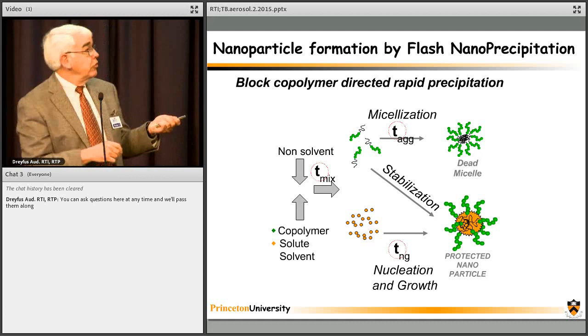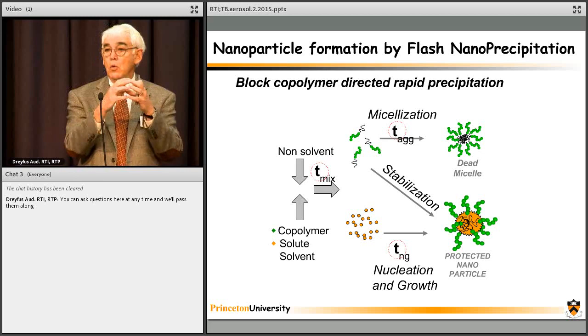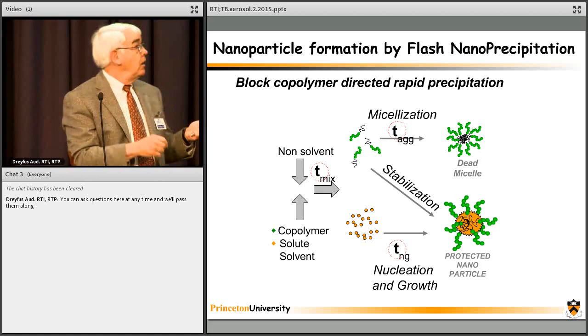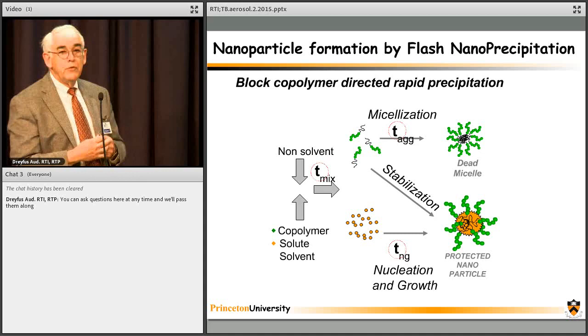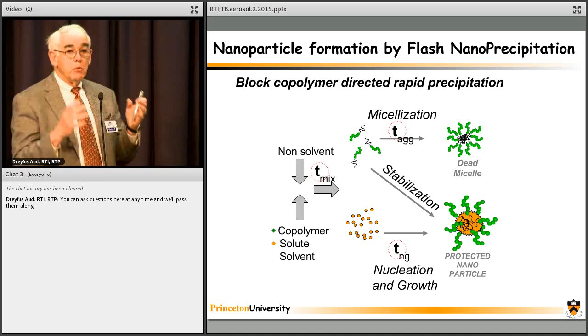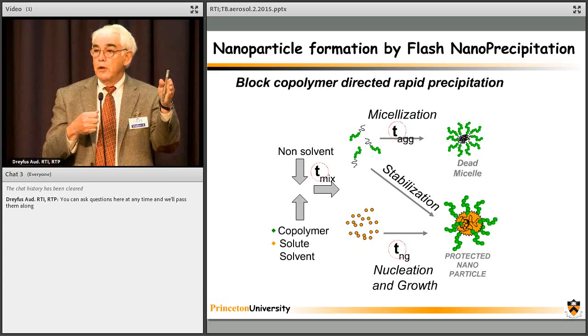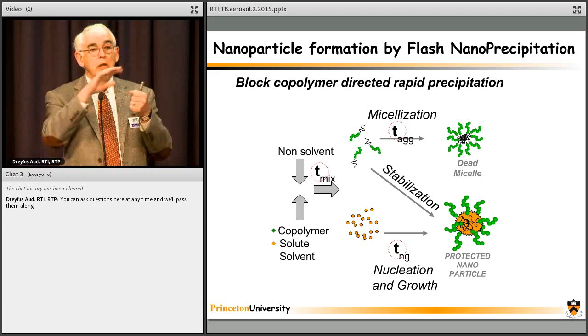So there are two different time scales here. There's a time scale of aggregation and growth of the core, or hydrophobic core, and a time scale associated with the micellization of those polymers as they diffuse around and hit. We need to balance those time scales, and that's something chemical engineers are pretty good at, is sort of competitive time scales. So what you want to have happen is when there is enough polymer adsorbed on that surface, it will stop particle-particle aggregation. So the start process is micromixing. The stop process is having adsorbed enough polymer on the surface that the steric layer prevents further aggregation.